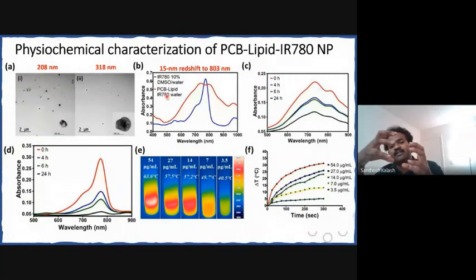And this aggregation provides a red shift. I mean, there's a 15 nanometer shift towards 803, which signifies that IR780 is loaded inside the nanoparticles and it's not bound on the surface of the nanoparticles.